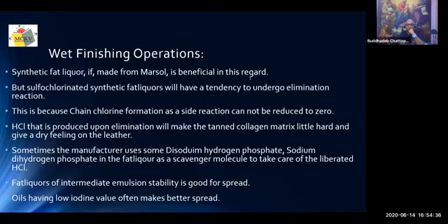The intermediate stability of the fat liquor is good for making leather because it will not go in and out. It is not likely to be retained much. Oils having low iodine value often make a better spread, because if you have a higher iodine value, it can go for polymerization and thereby a sticky mass can be generated, which will affect the lubrication between the fiber. It will just oppose the lubrication between the fiber bundles.